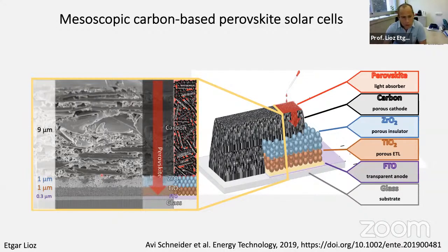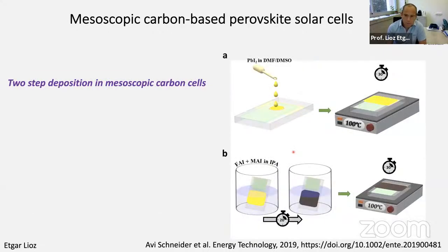also with some porosity, a carbon layer, a very thick one, as you can see in the cross section. Finally, when you print all those layers by screen printing, you drop the perovskite from the top, and this penetrates the whole way down. So we developed a two-step deposition for this cell. First, we drop the first precursor, which usually is the lead iodide or the lead halide, and then we dip it in the second one.